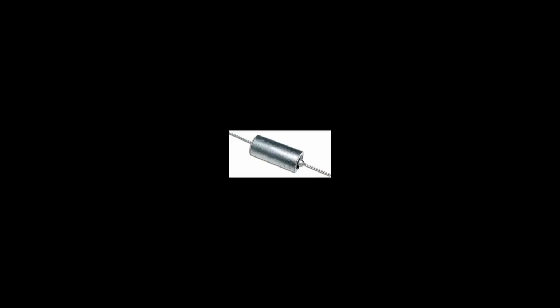Solid tantalum capacitors with crystallization are most likely to fail at power on. It is believed that the voltage across the dielectric layer is the trigger mechanism for the breakdown, and that the switch-on current pushes the collapse to a catastrophic failure. To prevent such sudden failures, manufacturers recommend 50% application voltage derating against rated voltage, using a series resistance of 3 ohms per volt, or using circuits with slow power-up modes, soft start circuits.